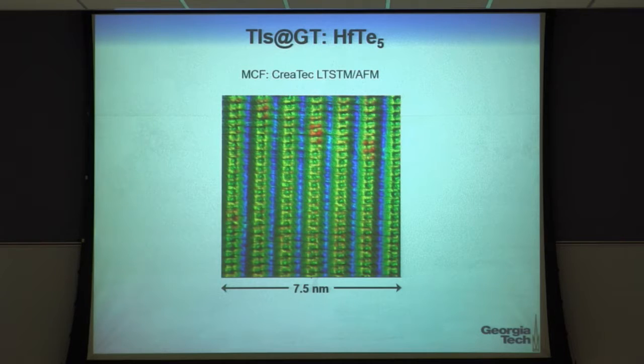Let me show you a little bit about what's going on here in Walter's facility, the materials characterization facility, where we have installed not so long ago low temperature scanning tunneling microscope and atomic force microscope that I dearly hope becomes a facility for the campus. Now these measurements are not easy, they're time consuming, but I think they're worth it in many cases, especially for these types of materials. So we are studying, for instance, hafnium pentatelluride, where we see atomic rows. These are double rows of tellurium atoms, and in between, in these blue regions, there are sort of double zigzags, which I don't show you on this picture. And there are some dopant atoms in here which appear with a slightly modified height. It's about 1 angstrom from top to bottom in height scale that you're seeing here.